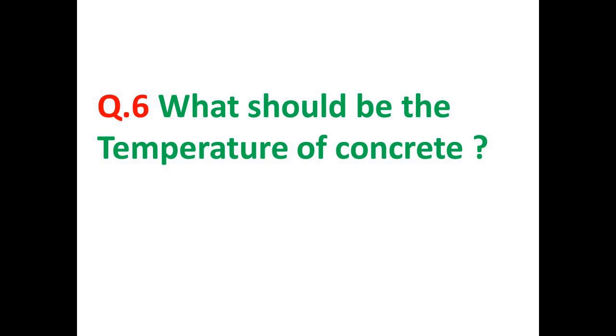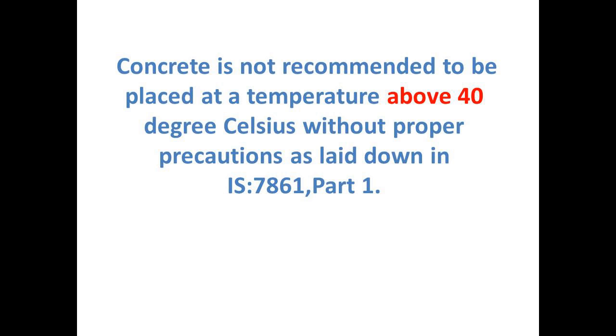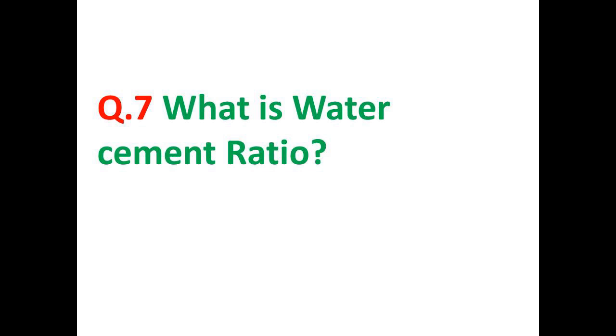What should be the temperature of concrete? Concrete is not recommended to be placed at a temperature above 40 degrees Celsius without proper precautions, as laid down in IS 7861 Part 1.